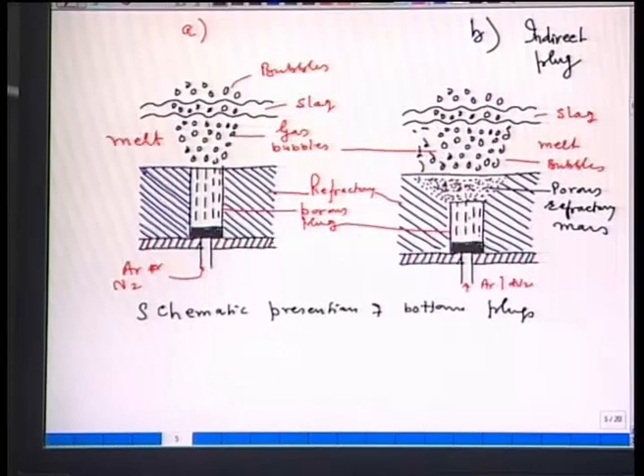In design B, which is an indirect plug, no doubt the plug is not directly in contact with the melt. Melt is in contact with the porous refractory, that is between the bottom of the melt and the top of the plug. A porous refractory mass is rammed, gas is injected through the plug, it discharges through the porous refractory mass and is injected into the melt. Obviously, the advantage of the indirect type of plug is that a large surface area of the bath will be covered, the stirring will be better, but then one has to also design, fabricate and manufacture the porous refractory mass, so that it allows the gas injection.